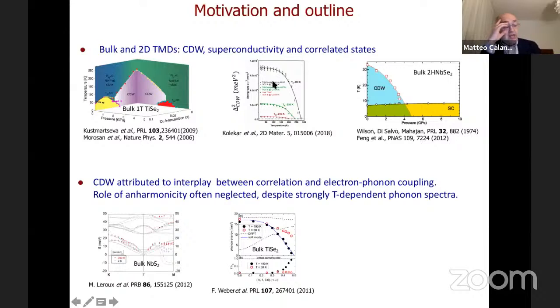Then there are many cases in which, for example, if you replace 2H niobium diselenide with the disulfide, so you replace selenium with sulfur, you don't have the charge density wave instability, but you still have superconductivity at practically the same critical temperature. It seems that in this system, niobium diselenide and disulfide, the coexistence between the two is almost accidental. So you can have the same superconductivity in the isovalent compound with sulfur without having charge density waves. They live in two separate worlds because they are mediated by completely different phonons. On the contrary, here the situation is not the same. Either you have charge density wave or you have superconductivity because they are mediated by the same phonon.